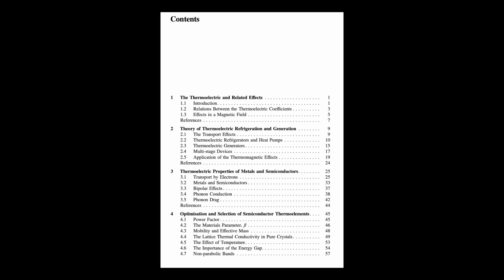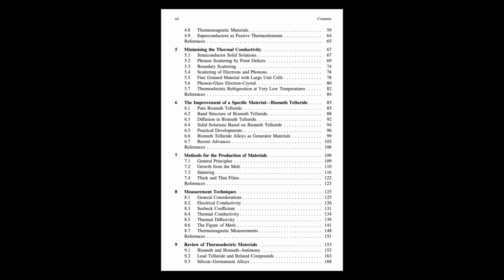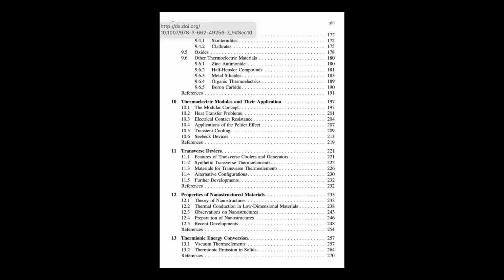And diffusion in Bi2Te3, why does that matter? Diffusion, atoms moving around within the solid, is important for a couple of reasons. When you make the material, you add dopants. Diffusion helps distribute them, but also when devices operate, especially at higher temperatures, like in generators, atoms, the bismuth, the tellurium, the dopants, can slowly move around. This unwanted diffusion can change the properties over time, degrading performance. So understanding and controlling it is vital for long-term reliability.